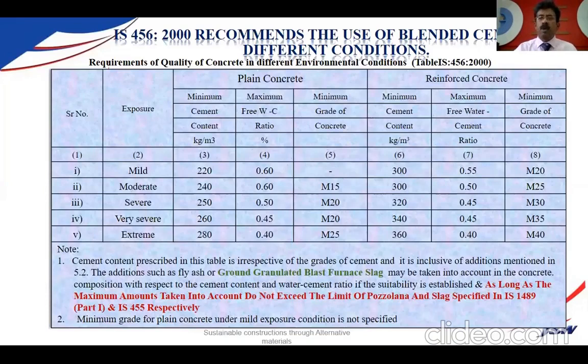So the Indian code permits usage of these materials, whether it's slag or fly ash. The mix design itself they have given, so you can replace based on the percentage. Fly ash you can go up to 35%. GGBS, if you are using it, can go from 25 to 70%. Okay, that is the minimum requirement. If you are going for mass concrete applications where you have a raft of 1.5 meters, 5 meters and all, people have used it in India up to 60% GGBS, replacing the OPC cement.